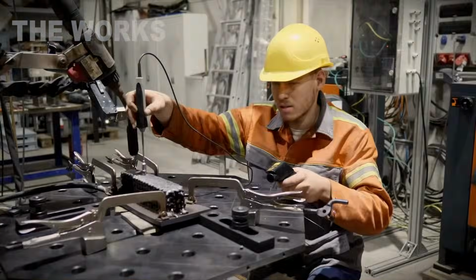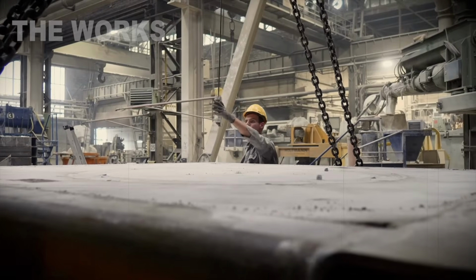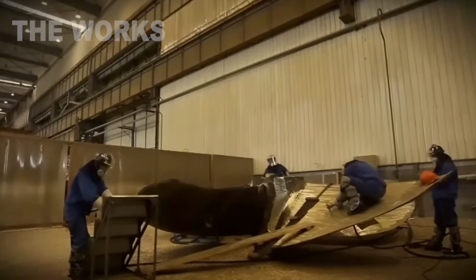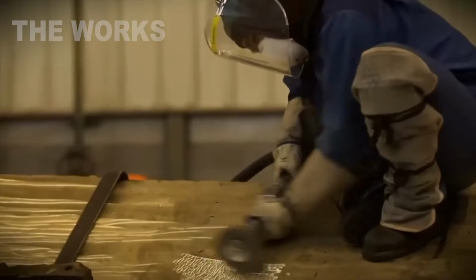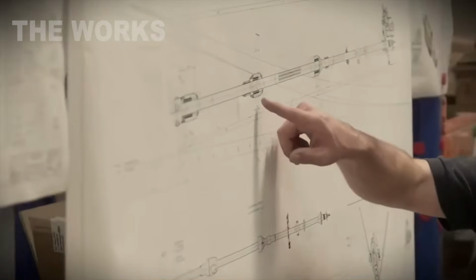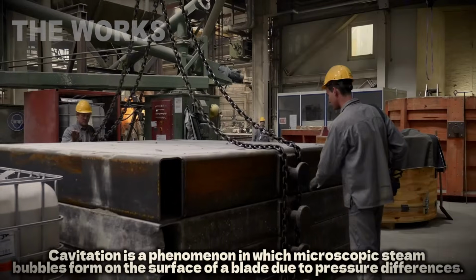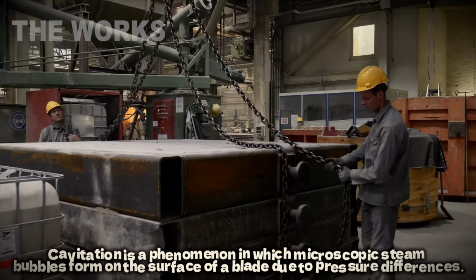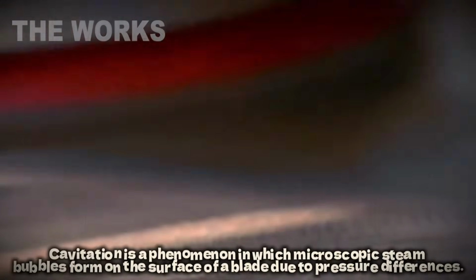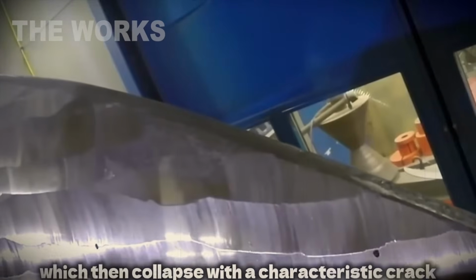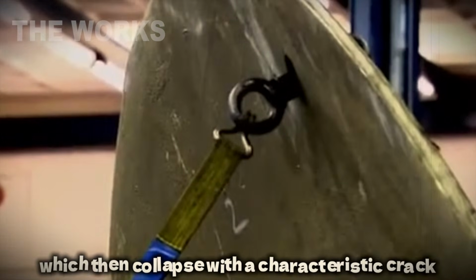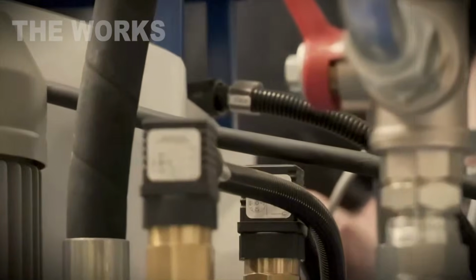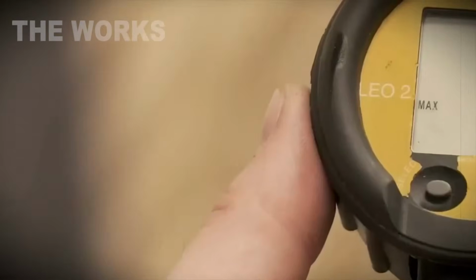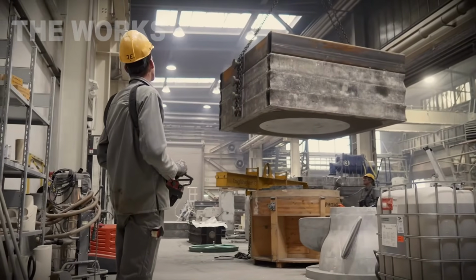This brings us to the main theme of this facility: silence. A warship, and especially a submarine, must be as quiet as possible. The propeller is the primary source of underwater noise. There are two mechanisms: mechanical noise from imbalance and vibration, and cavitation noise. Cavitation is a phenomenon where microscopic vapor bubbles form on the blade surface due to pressure differences, then collapse with a distinctive crackle. Each pop is a micro-impact that, over time, destroys even bronze, leaving small pits on the surface.